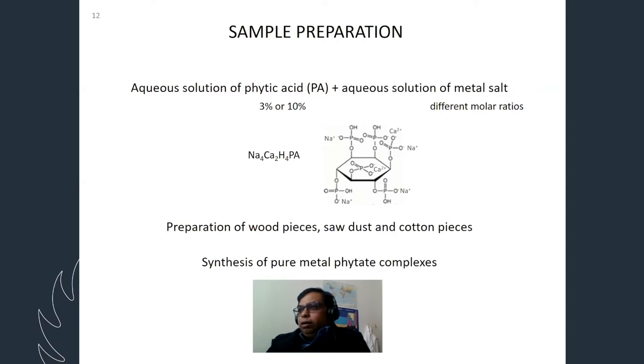In different cases, we added different metal ions, especially sodium and calcium, and also in different molar ratios. As you can see here, the sodium 4, calcium 2, and the protons. So we varied their relative ratio in the formulation.